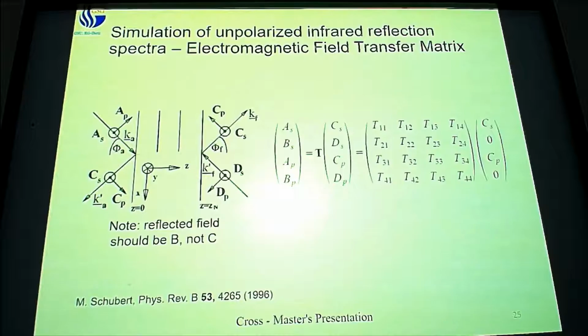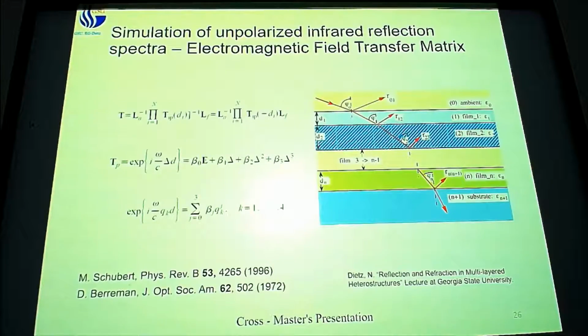The way that we model this is with a matrix. We can correlate the incoming and outgoing waves with the incoming and outgoing waves on the other end of the layer. This is called the transfer matrix. There's a nice elemental representation here, but we need to define that. So, some work done by Berreman and Schubert: if I have a transfer matrix for each layer, I'll need to multiply all of those transfer matrices together, combining that with an incoming and an outgoing term in order to define the reflectance from my model.